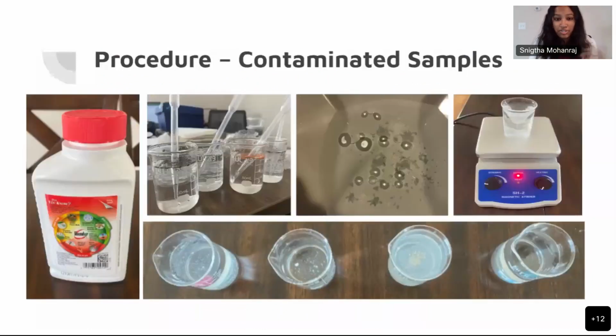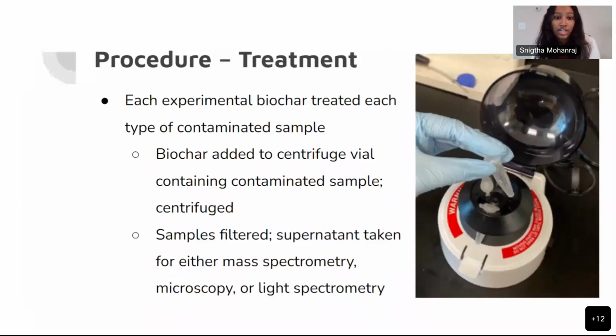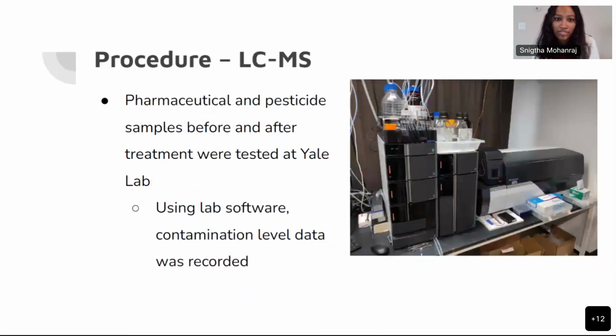So these pictures just show some of the contaminated sample preparation. And then each experimental biochar treated each type of contaminated sample. The biochar was added to the centrifuge vial containing the contaminated sample. It was centrifuged, the samples were filtered, and then the supernatant was taken to the corresponding analysis. So the first analysis was the liquid chromatography mass spectrometry, which is the outside lab work at Yale Labs. And using the lab software, contamination level of pharmaceutical and pesticide samples was recorded.